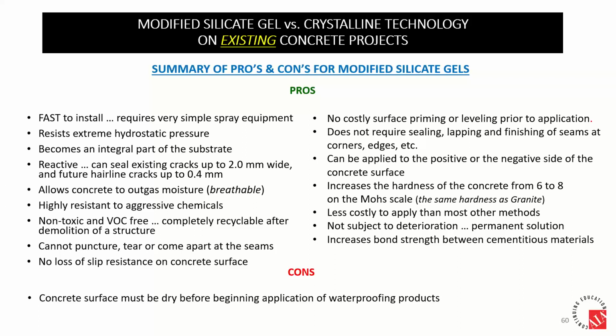It's highly resistant to chemicals like de-icing salts. It's non-toxic, VOC-free, completely recyclable after demolition. You cannot puncture, tear, or pull apart at the seam. You don't lose any slip resistance that concrete naturally provides. There's no priming or leveling required like with some coatings. There are no seams, no overlapping, no corners or edges. Can apply to positive or negative side, increases the hardness of the concrete surface. Low cost, not subject to deterioration or wear, and it actually increases the bond strength of the cementitious materials. So a lot of pros for the silicate gel strategy.